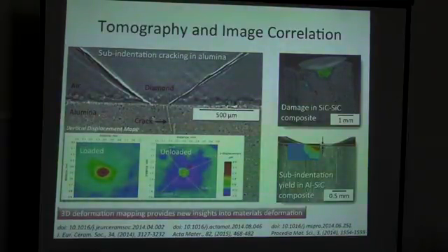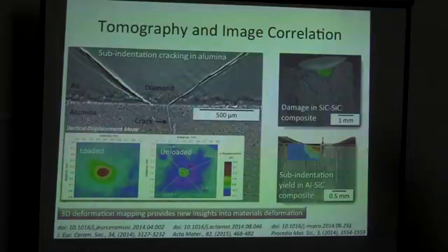So any kind of study where you're trying to measure deformation at the fine scale in 3 dimensions, I really would recommend these techniques. The key requirement, of course, is you've got to be able to get X-rays to it, and also you have to have speckle, a microstructure that gives you features. You don't need much, as the bottom right image shows, you don't need much contrast, but you need something. So unfortunately it's not a panacea, you can't look at everything.